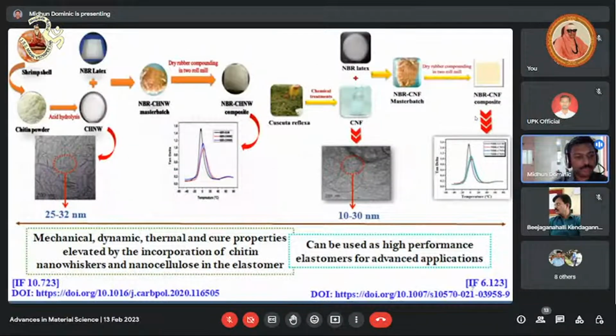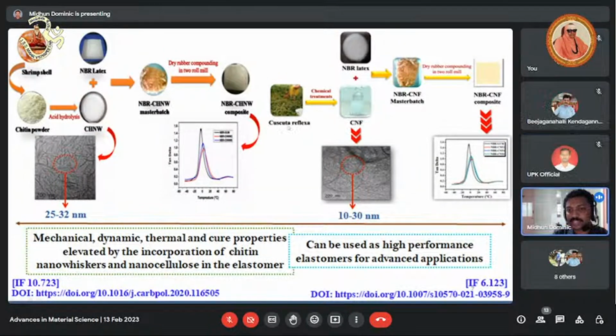Okay, so we have developed another material, cellulose nanofibers from a common parasitic plant seen in Kerala, that is Cuscuta reflexa. We have converted it into cellulose nanofiber and mixed it into NBR, nitrile butadiene rubber. The CNF composite is prepared, and we have got excellent properties. And again, chitin powder is prepared from shrimp shell waste, and this chitin powder is mixed with NBR latex. NBR is polar in nature, so we have got excellent reinforcement properties.